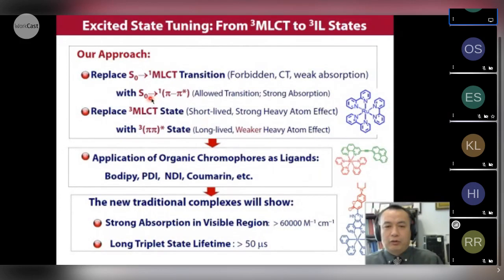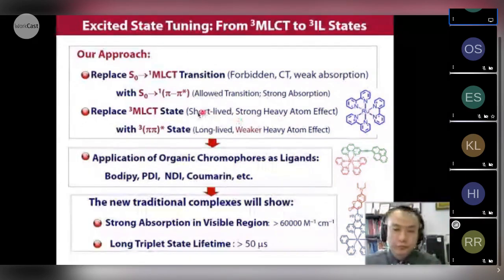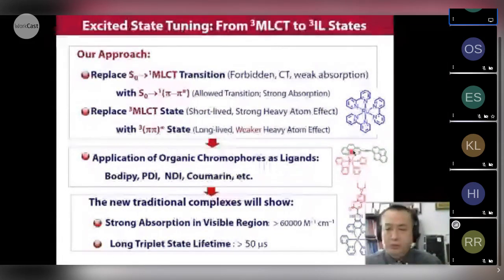We also know that for π-π* transition, it has a very good molecular orbital overlap. That means we will have a higher transition probability. Accordingly, we will have a stronger absorption of light. So by changing the excited state, we can change the photophysical property of the complex. If we switch from MLCT state to π-π* state, we will have a weaker spin-orbit coupling for the π-π* triplet state, because in this case, the contribution from the metal to the triplet state is very small. With smaller spin-orbit coupling for the triplet state, we will have a longer triplet lifetime.